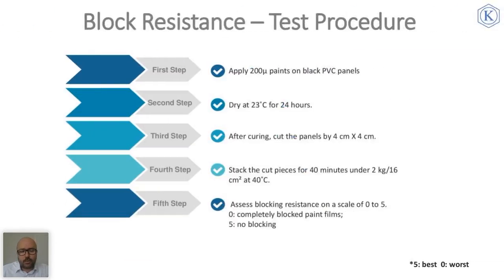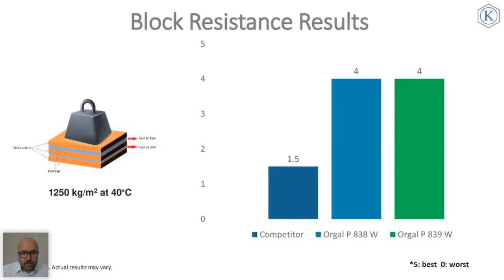First test result where I'm going to show you is about block resistance. Block resistance is tested after application on black PVC panels and drying 24 hours at room temperature and pressing the panels with 1,250 kilograms per meter square at 40 degrees Celsius. As you know, there are several different block resistance test methods in our industry, and this is a method that we mostly apply for exterior wood coatings, mostly for DIY applications.